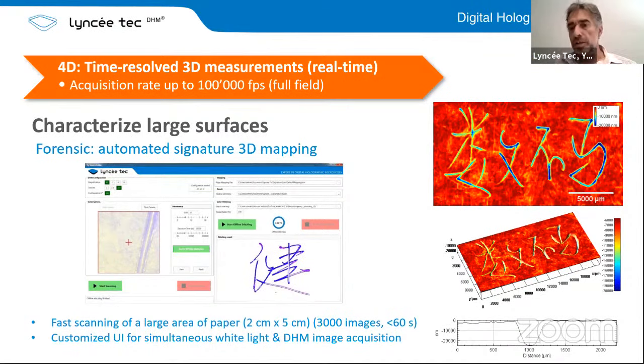So you have steep flank, it's rough. We need a 20x objective with a field of view of 300 times 300 micrometer, but you don't sign over 300 times 300 micrometer, but on centimeter square. So this image is a stitching of more than 3,000 images stitched in less than 1 minute. So we can also look at large sample to see what happened very quickly, and we can react.